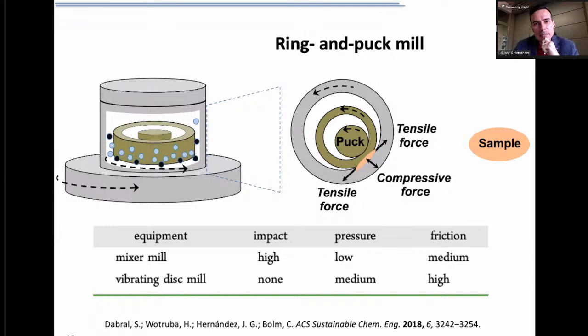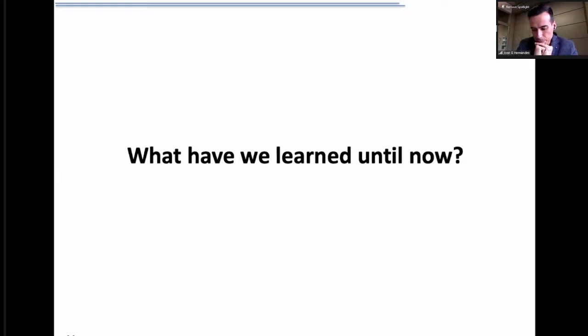So what we have learned until now, I think, is that we can activate mechanophores in polymers, not only by sonication, but that there is a growing body of evidence that ball milling techniques can also be used for doing that, so that we can harness the mechanical force from milling techniques, and we can use the polymer backbone to transduce mechanical force all the way to a mechanophore, which is planted or embedded within a polymer material. Also, we observed that sonication and ball milling can cause the same effects on a polymeric material, but sometimes they can even complement each other. And if you want to gain directionality, you can find already available techniques which can help you to increase the directionality, something that seems to be lacking when you do the reactions by ball milling.